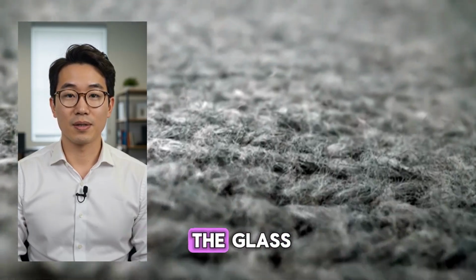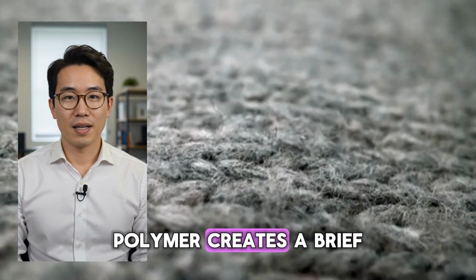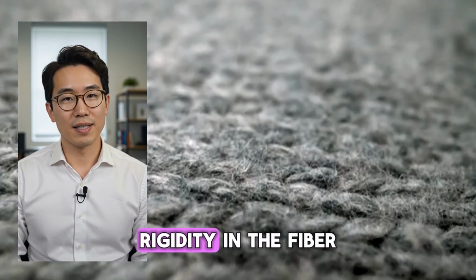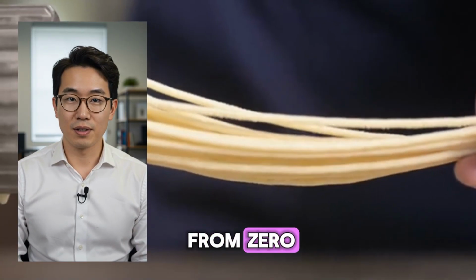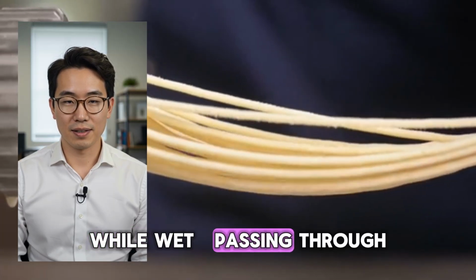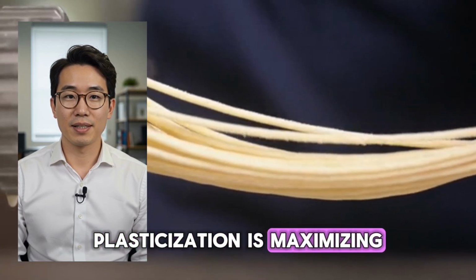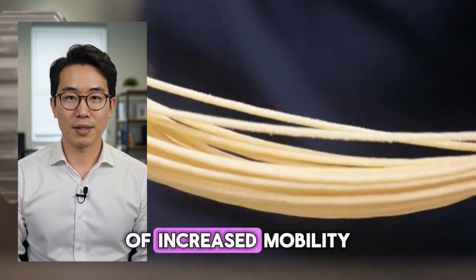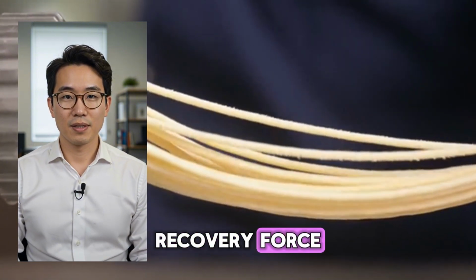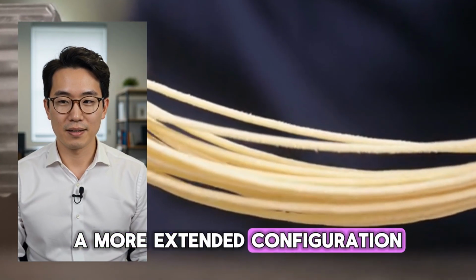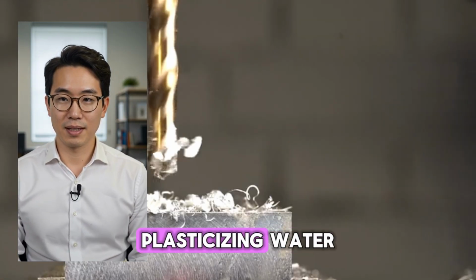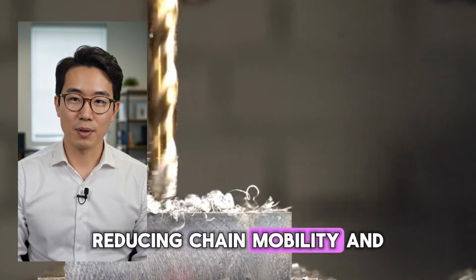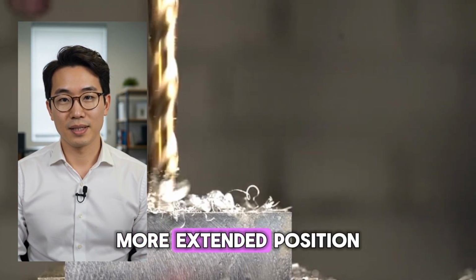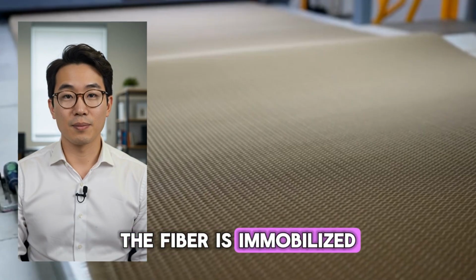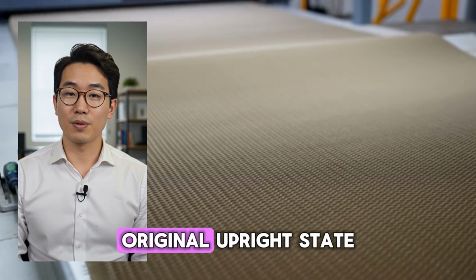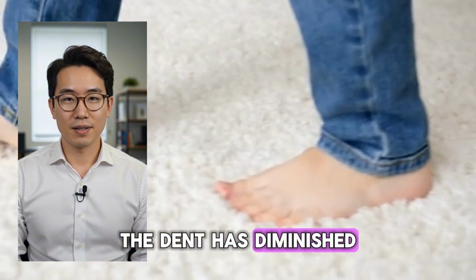The cold phase below the glass transition temperature of the dry polymer creates a brief period of extreme molecular rigidity in the fiber. As the fiber warms from 0 toward room temperature while wet, passing through the range where plasticization is maximizing chain mobility, the combination of increased mobility and the slight elastic recovery force drives the chains toward a more extended configuration. The drying phase removes the plasticizing water, progressively reducing chain mobility and locking the chains into their new, more extended position. The fiber is immobilized in a configuration closer to its original upright state. The dent has diminished or disappeared.